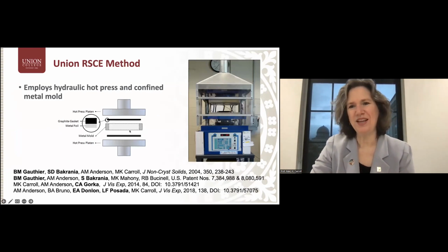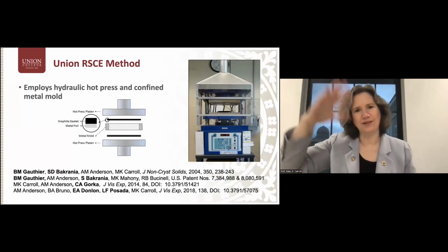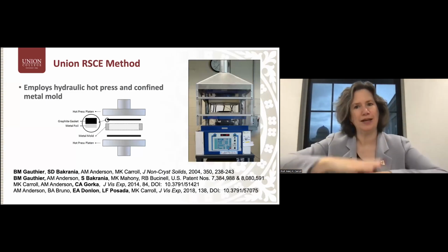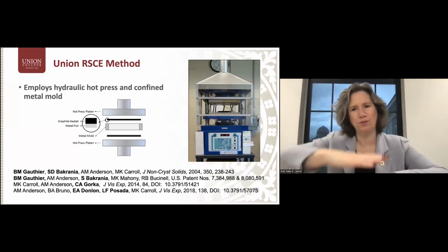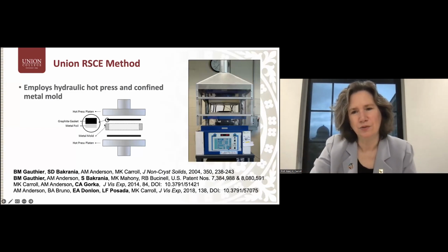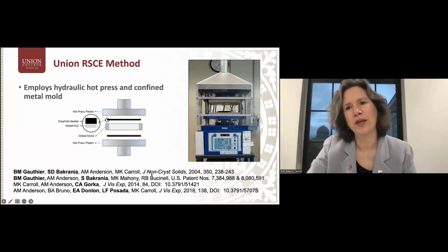And so if we really want to make very monolithic aerogels, what we do is we initially use gasket material to seal the bottom of the mold. We pour things in, so we do an initial sealing. Hot presses can be used, for example, to laminate things, so this is something that's relatively easy to do. We push down so that this bottom part is then sealed. We pour the liquid precursors in, put fresh gasket material, and then do the process. When it comes out, we can then push the aerogel through.